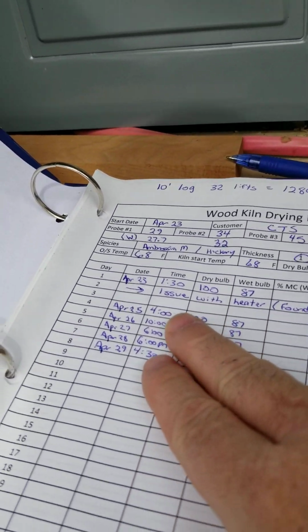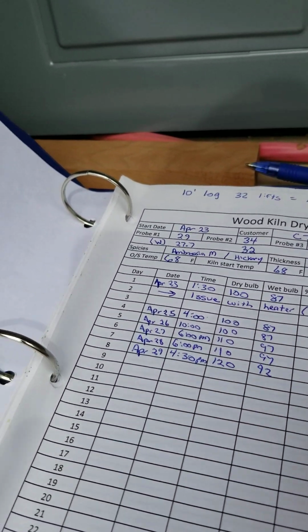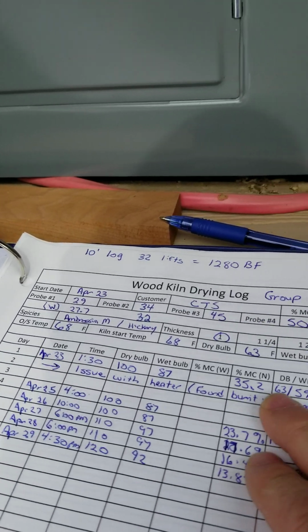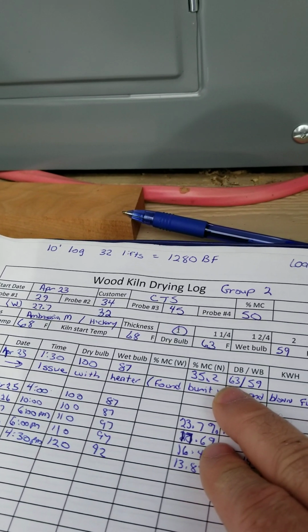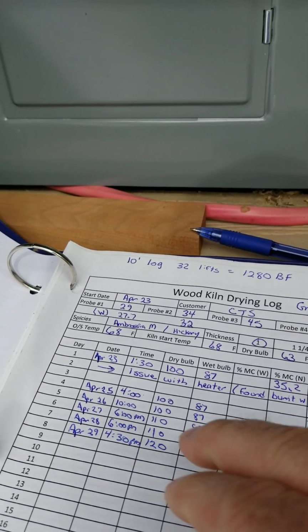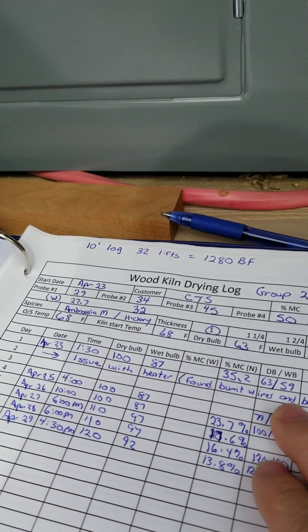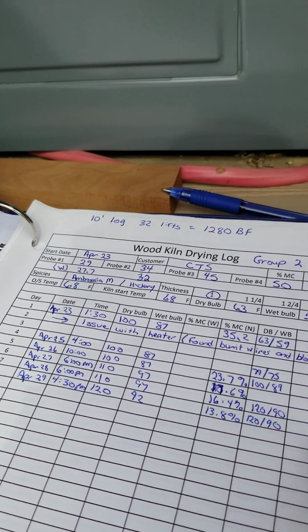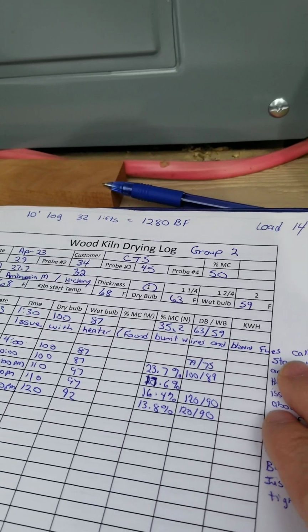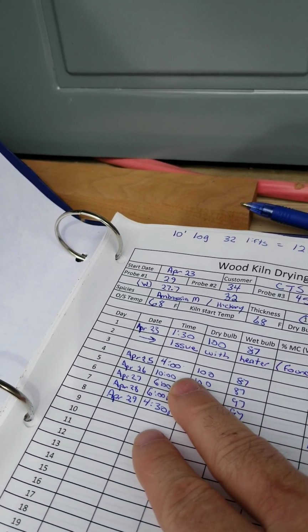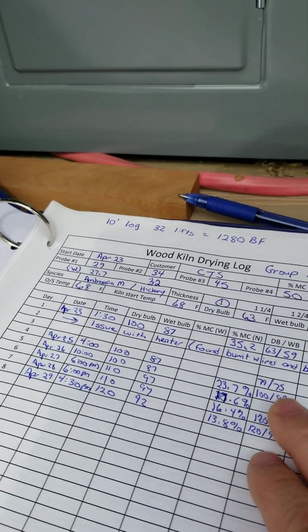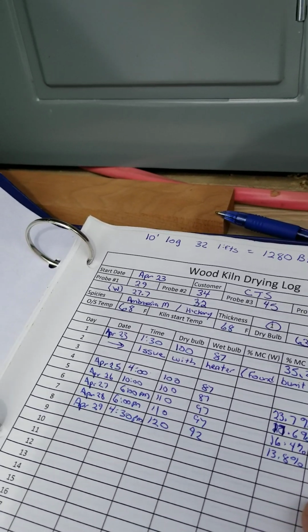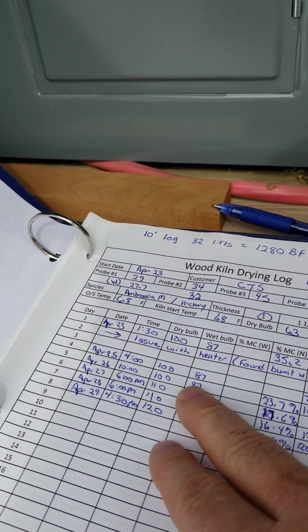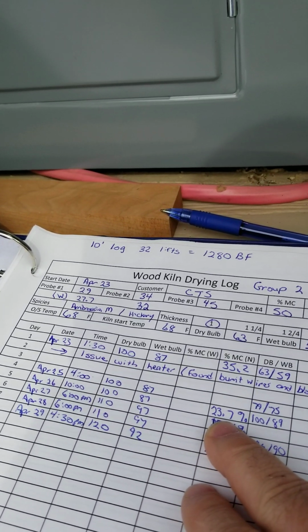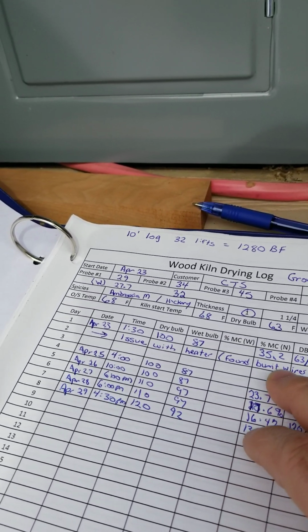So every day we come in and we write these numbers down. The average moisture in the kiln was 35.2%. We had a bit of a breakdown the day we put the wood in the kiln. There was an issue with the heater we had to fix. Then we re-established the kiln with the heater working. Actually, it was a span of days.